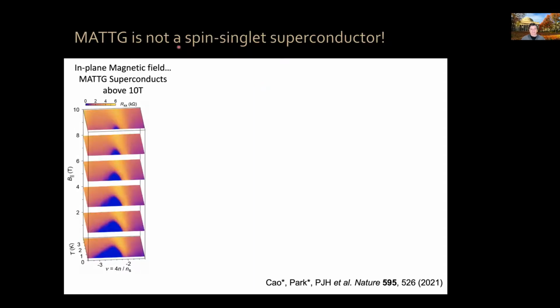Now, another interesting development has been that we have realized that magic angle twisted tri-layer graphene is not a spin singlet superconductor, okay? Conventional superconductors are spin singlets, spin up, spin down, okay? Magic angle twisted tri-layer graphene, if we measure the superconducting dome, okay? Temperature versus doping. And now we look at what happens when we apply a parallel magnetic field so that we can look at the effects of Zeeman field on the system, okay?